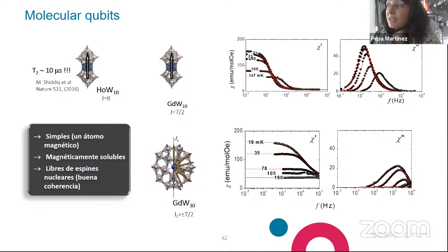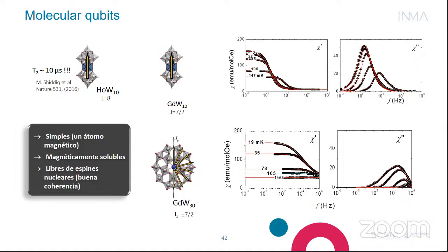Yeah, also consider that the sensitivity of commercial SQUIDs is not at all as large. Even if the flux noise of the SQUID itself can be very good, the coupling factor to the sample is always much worse. So you lose sensitivity through the coupling factor. Right. I agree with you completely on that. So you get much better sensitivity in terms of spin sensitivity, but you are getting a better flux sensitivity also.